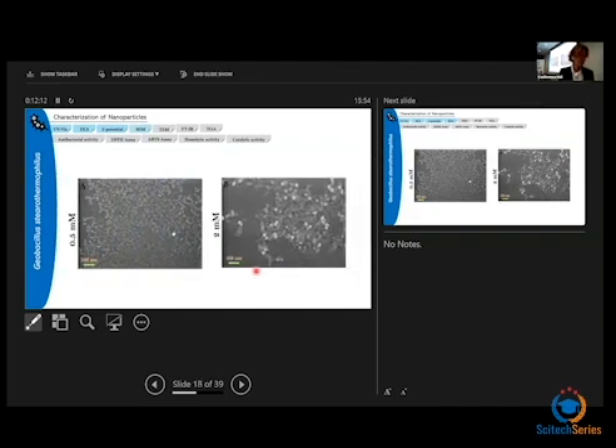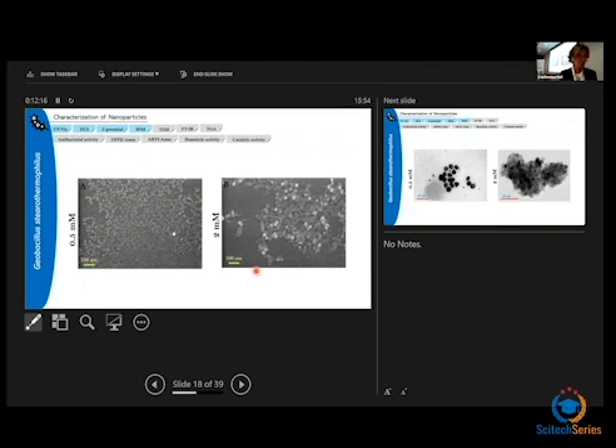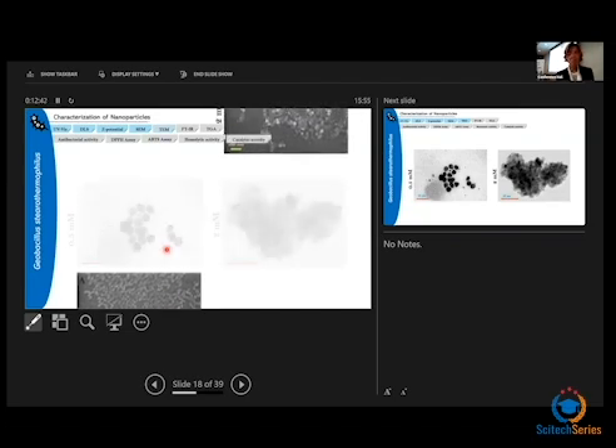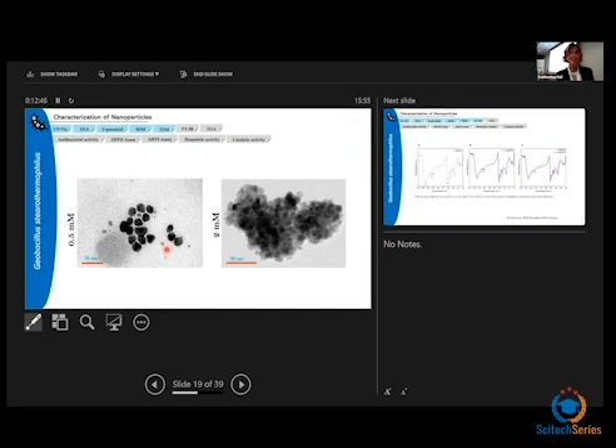The formed silver nanoparticles were also analyzed through scanning electron microscopy and transmission electron microscopy, and here are reported the results of the SEM analysis. As can be seen, both samples exhibit a subspherical shape with only slight differences in size, which we can see better from the TEM analysis, but with a very different texture. The nanoparticles synthesized using 0.3 millimolar have a subspherical shape, and the dimension measured was around 17 nanometers.